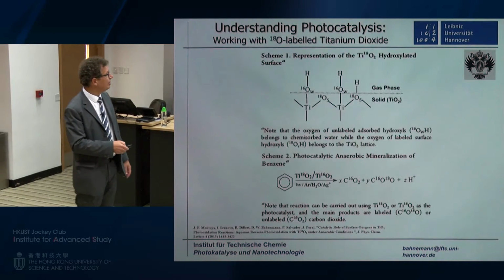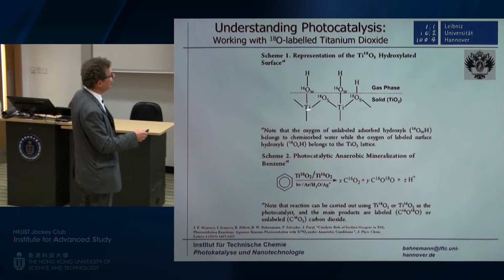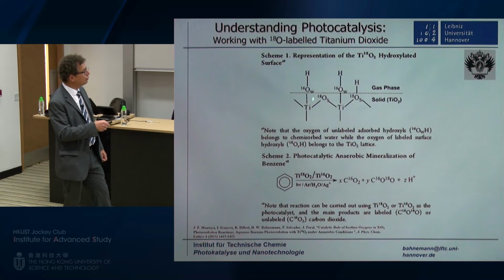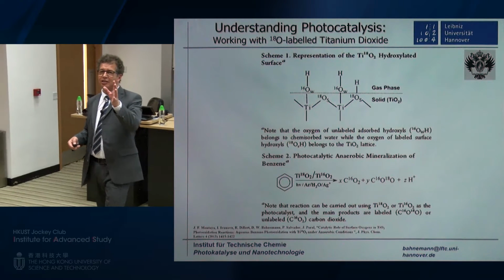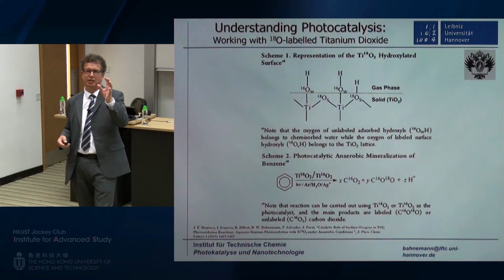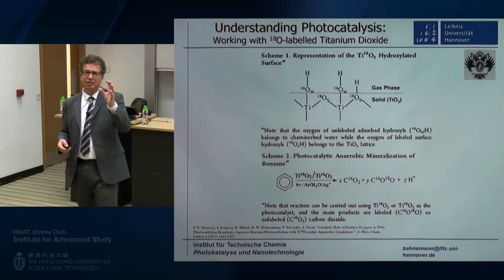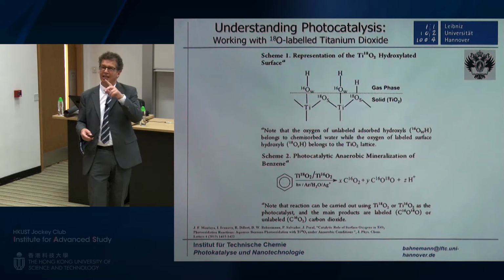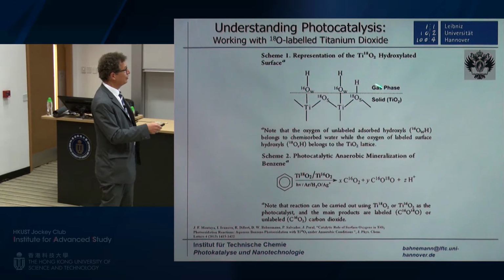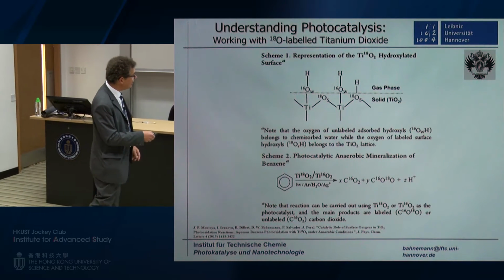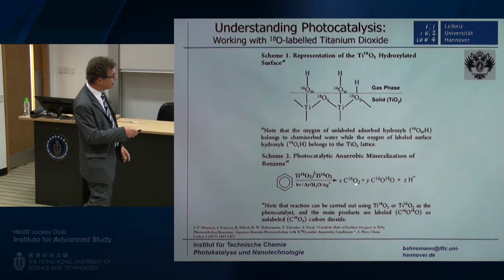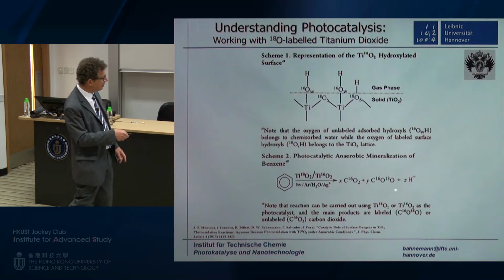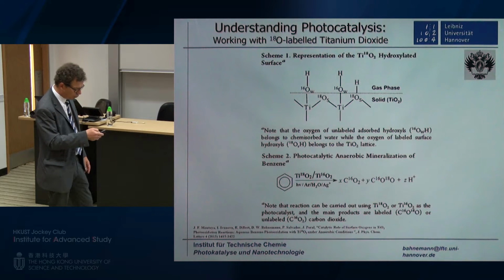Why do we think this is happening? We think this because we prepared our own TiO2, containing not O16 but O18 in the matrix. We use the same synthesis that I showed you before, where titanium tetrachloride reacts with water, but now it's not H2O16, but H2O18. So it's easy to synthesize, it just costs a little more money. And then we looked at the oxidation of benzene to form carbon dioxide, and we checked with mass spectrometry the amount of carbon dioxide containing O16 and the amount of carbon dioxide containing also some O18, which can only come from the TiO2 in the system.